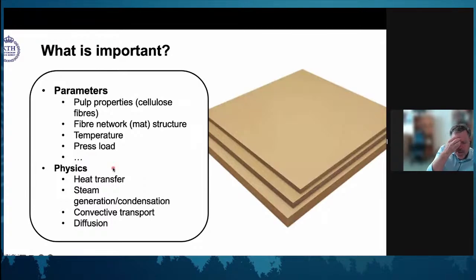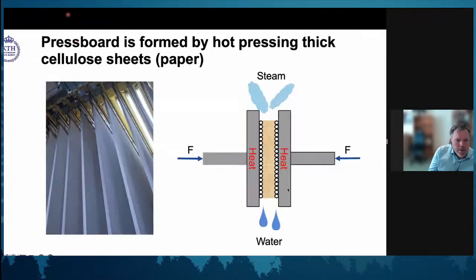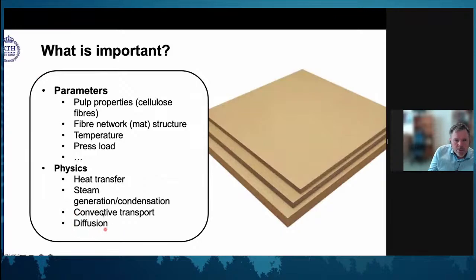And then you start to think the next step is, with all of these parameters, what are the physics of this process? It is heat transfer, of course, because we try to apply heat. We create steam in the process. Depending on the surface properties of cellulose and the temperature of fibers and the temperature at different positions, you can even think that you are generating steam and that it can condense again on a surface. We're also interested in convective transport. Even if we heat something up in the center of the sheet, it needs to get out of the sheet and be transported away, and that is the convective transport. And of course, there is some element of diffusion. So it's a set of physical phenomena that is controlling this.